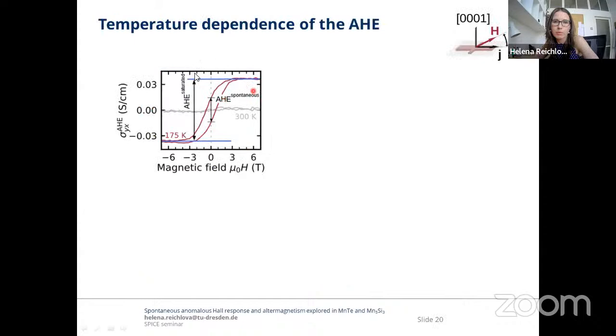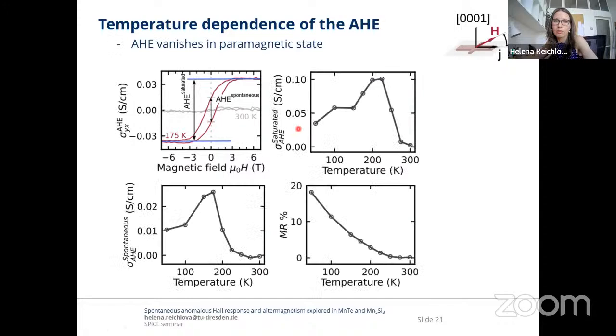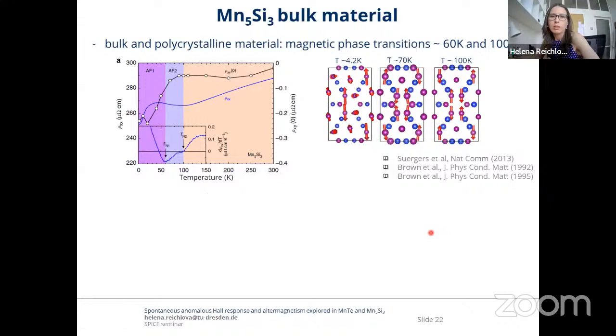Here I show one example of the magnetization loop measured on the manganese telluride sample. We have defined a value of the saturated anomalous Hall effect. This is the value with applied magnetic field, but also the spontaneous one, which is present in zero magnetic field. And when looking at the temperature dependency, we see that both behave similarly. And exactly as expected, they are absent in the paramagnetic state. The Néel temperature of manganese telluride is around 300 K, the same temperature where the magnetoresistance disappears. So this was our first relatively well-known material, which we studied, the manganese telluride semiconductor.